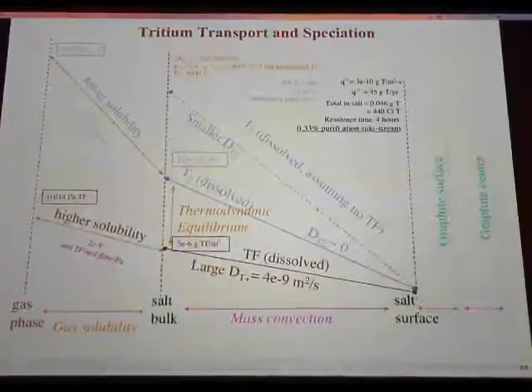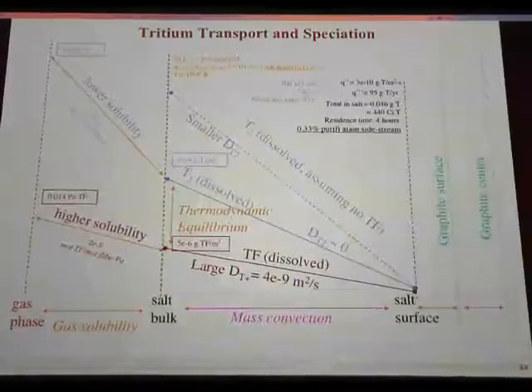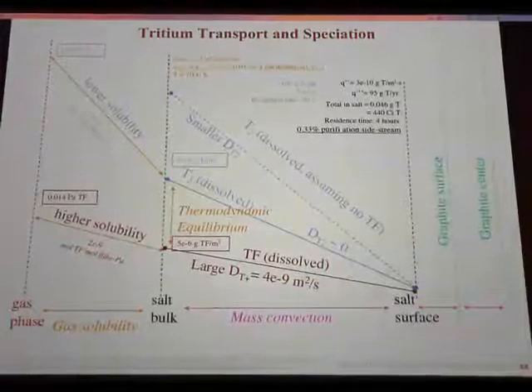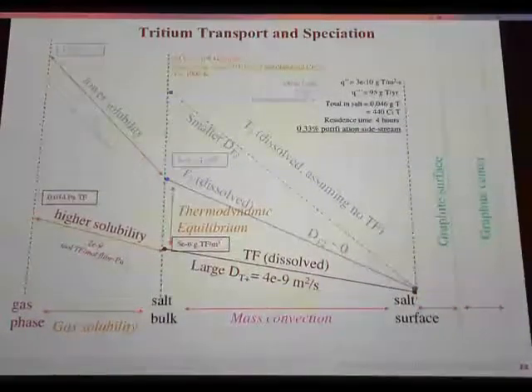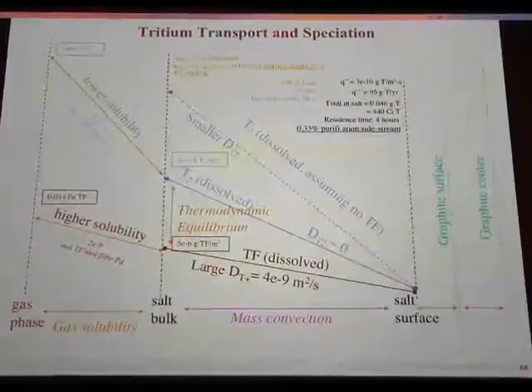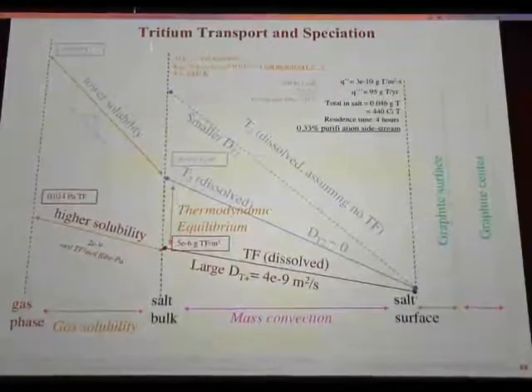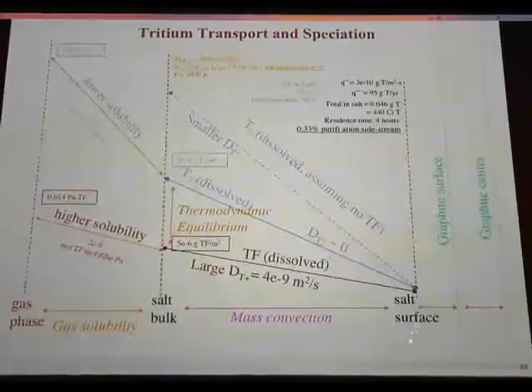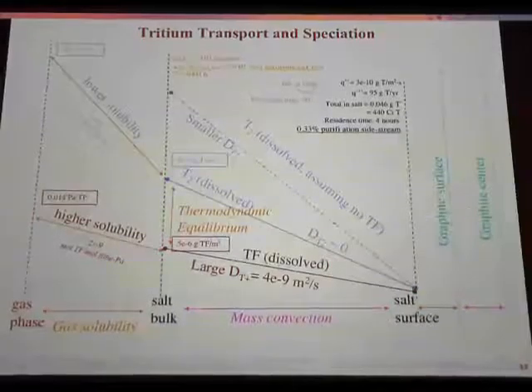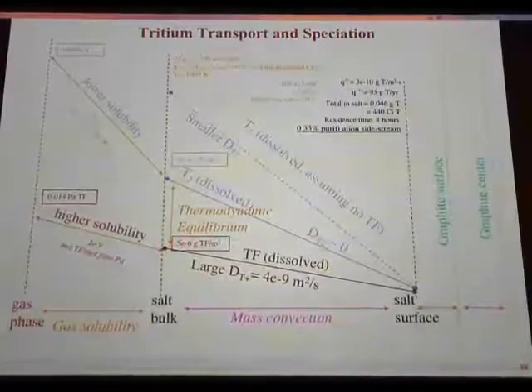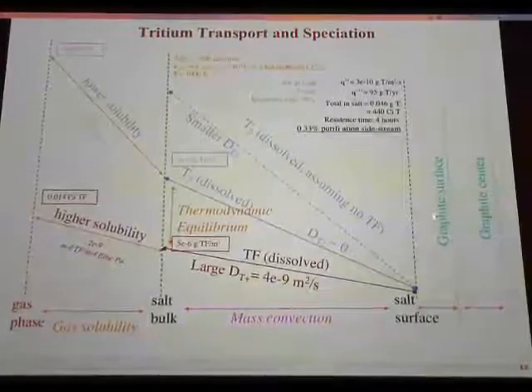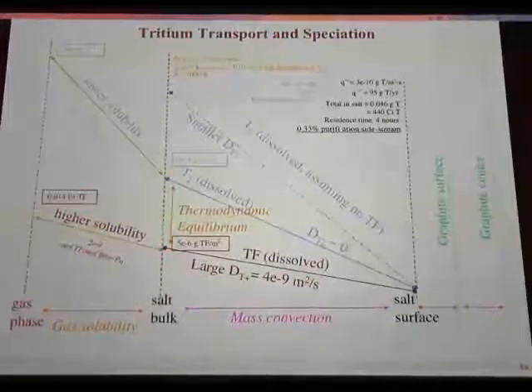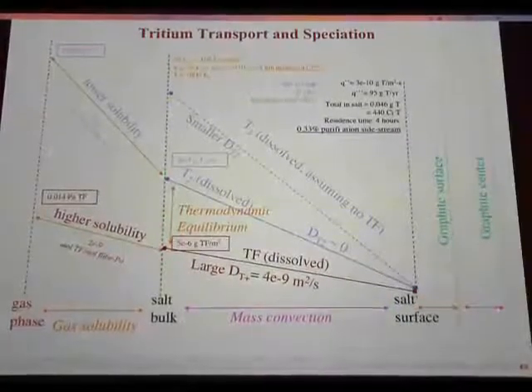So let's look at the mass transport problem. And I know it's a very busy slide, but bear with me. It was important that I put everything in one picture. Okay, so I'll walk you through it. So what you see here is this bulk salt and the salt surface. So here you have the salt-graphite interface. That's the graphite surface, and that's the salt surface. And then you have the graphite bulk, and then you have the gas phase.